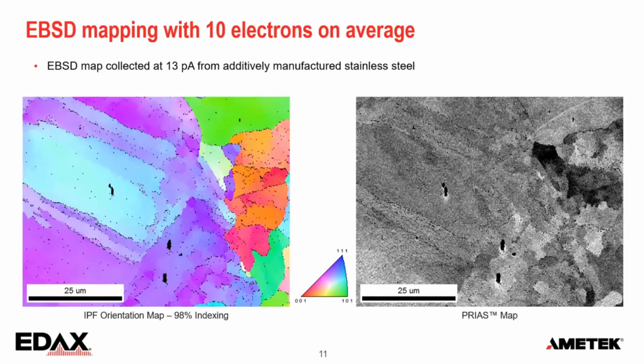And we can go a little bit lower when we have really nice patterns. This is on 3D printed steel, 13 picoamp of beam current. Material gives good patterns normally to begin with, so we don't need much. And then we can do EBSD mapping with about 10 electrons per pixel on average. So that's close to the lower limit of what is possible.